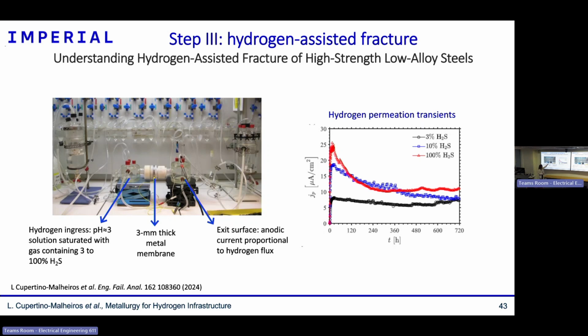And here on the exit side, I am again detecting hydrogen that has been absorbed into my steel membrane. So what you can see here is this flux, or this current density, that is proportional to the hydrogen that gets absorbed in the steel over time, here during 30 days. And this was done for H2S pressures from 3 to 100, and as I said, H2S favors hydrogen absorption. That's why for the red curve, you get higher values of hydrogen absorption here in the beginning.